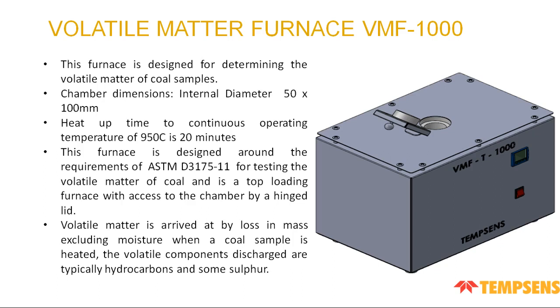Heat up time to continuous operating temperature is 950 degrees plus minus 20 degrees in 20 minutes, and the furnace is designed as per the standard ASTM D3175-11 for testing of volatile matter of coal, and it is a top loading furnace with access to the chamber by a hinged lid. And volatile matter is arrived at by the loss in mass excluding moisture when a coal sample is heated. The volatile matter discharged is typically hydrocarbon and some sulfur contents.